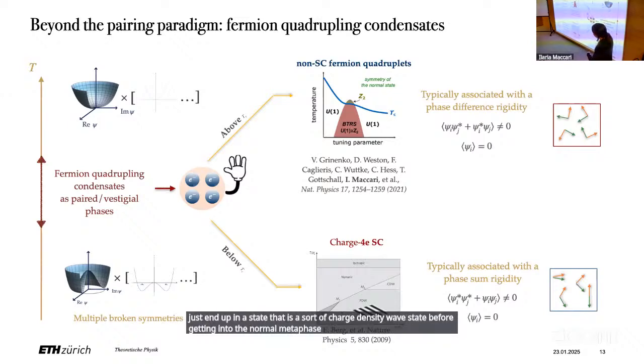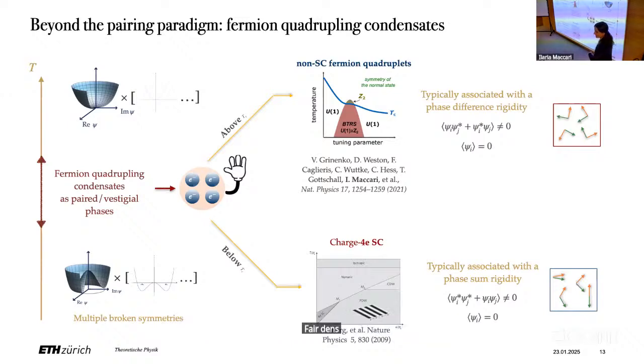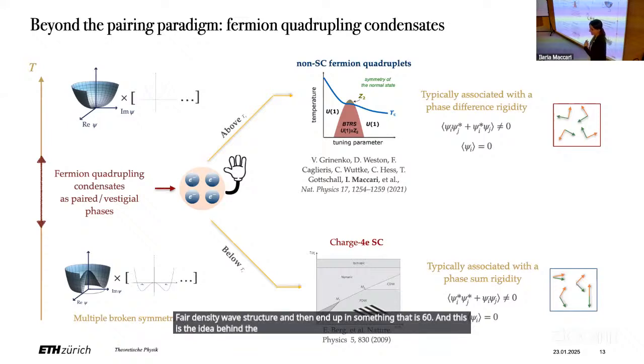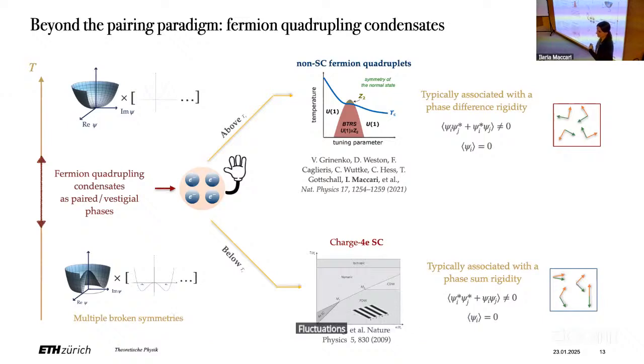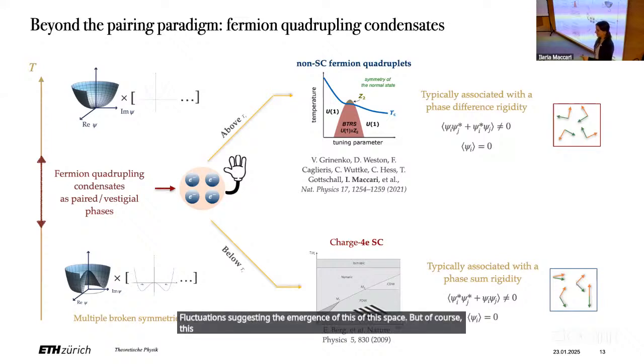But in principle, one can realize more complicated pair density wave structures and then end up in something that is 6e. And this is the idea behind the experimental paper on the Kagome material, where they observed these h/6e fluctuations, suggesting the emergence of this phase. But of course, there are also many harmonics that overlap, so it does not completely rule out the possibility that this is not the case. So more experimental evidence is needed.